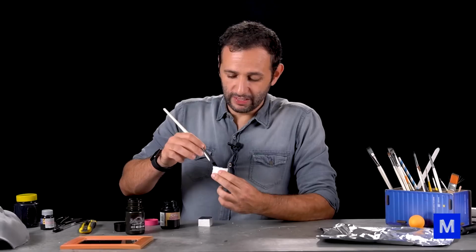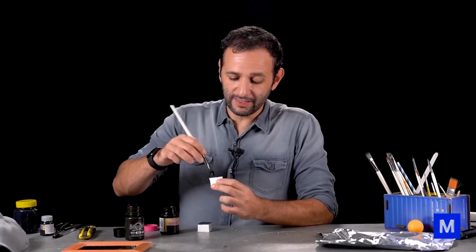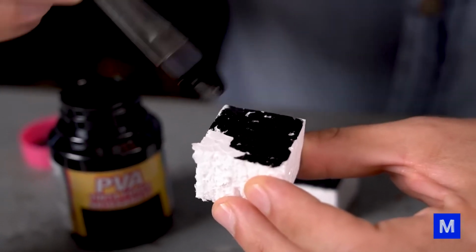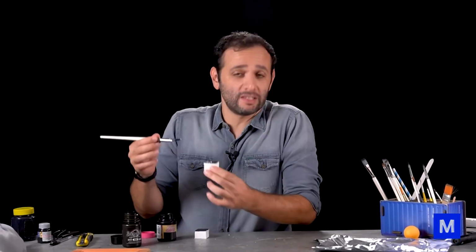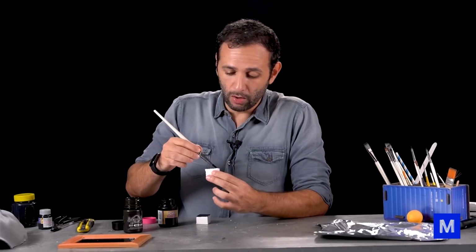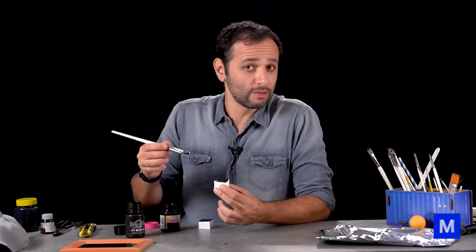A lot of people ask me if this paint couldn't be very useful for us to make that solar water heating at home. After all, solar heating is based on the absorption of light, on the transformation of light into heat. So if you use a paint that absorbs almost 100% of the light, it could be very useful. But not exactly. This paint is very expensive, and it loses its super light absorption if it gets dirty, if you touch it, or anything like that. And one more thing, regular black paints also absorb a lot. They absorb about 94%.